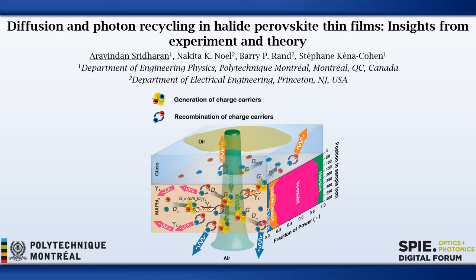The optical power entering the film is dissipated into four main processes, as shown on the right-hand side stack plot. When a photon is emitted, it can have one of four different outcomes: direct reabsorption, waveguiding which also includes possible reabsorption along the way, substrate emission, or emission into free space.